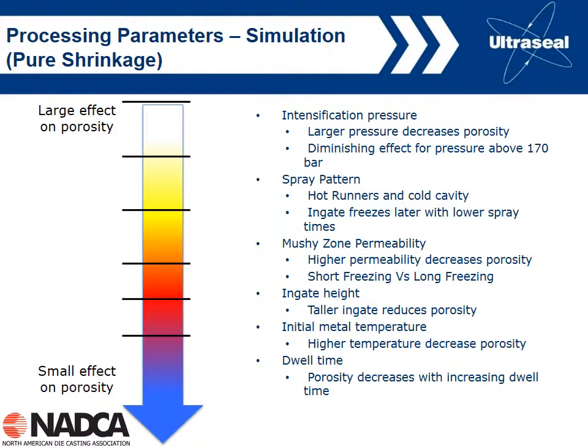And so at the top, we've got intensification pressure, and both the literature, simulation, and also our own experience tells us that intensification has by far and away the largest impact on shrinkage porosity. Unfortunately, what we find, though, is above 170 bar or so, 2,500 psi, we find that intensification pressure has a diminishing return. What we mean by this is, for instance, if we don't intensify, if we have a zero pressure intensification, we're going to get about 6% porosity, because that's the volumetric contraction that we get upon solidifying aluminum. If we apply 2,500 psi, maybe we can shrink that down to 1% porosity or so.